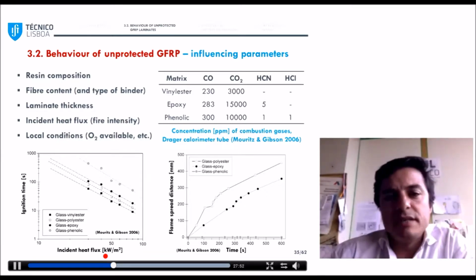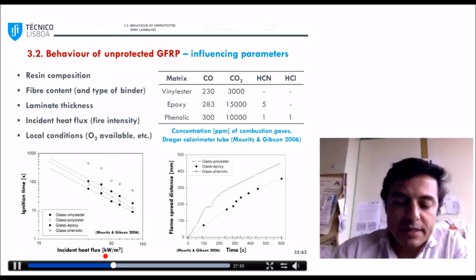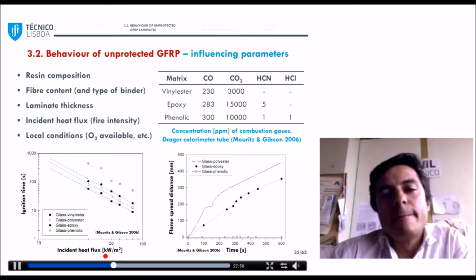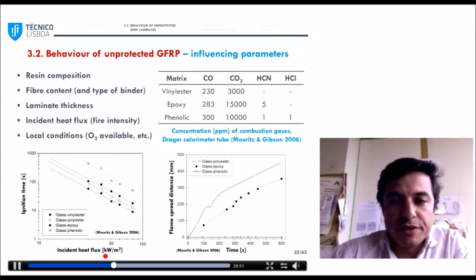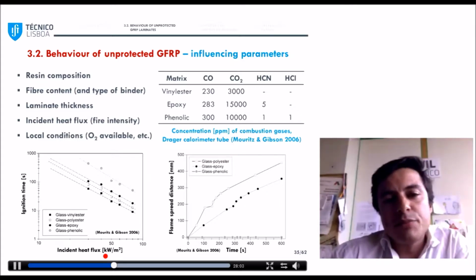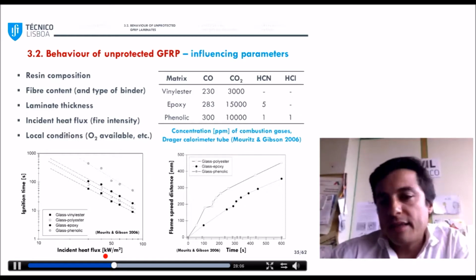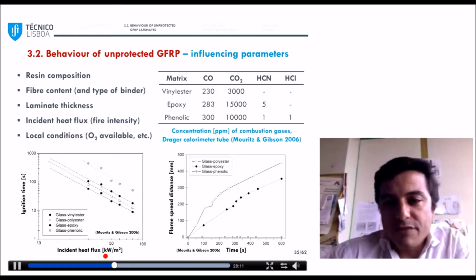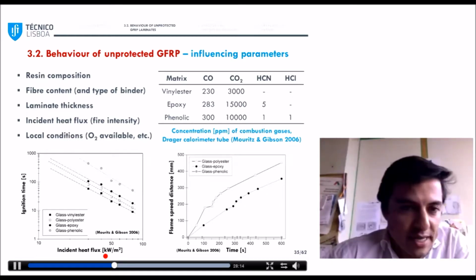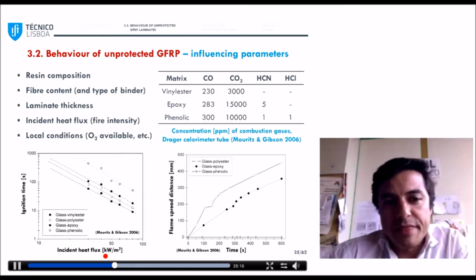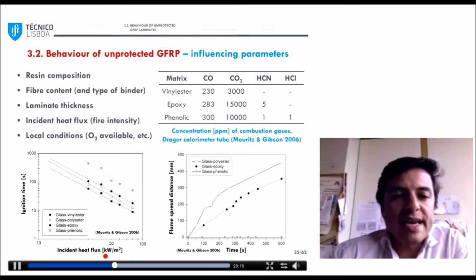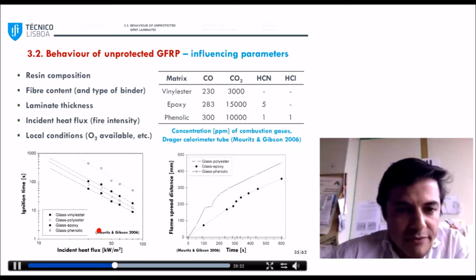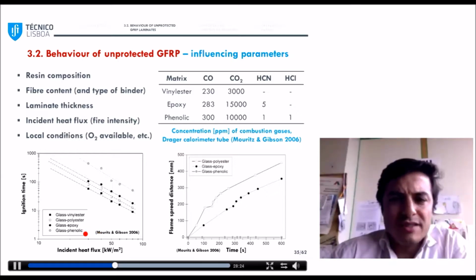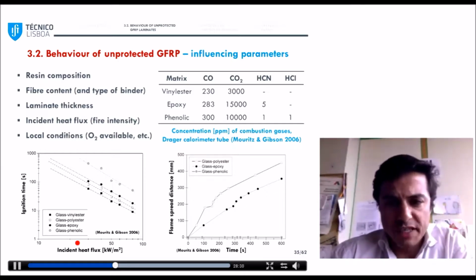So for unprotected GFRP material, and we will then see what happens when we use protections, there is plenty of literature from different industries, and previous results basically show that the fire reaction behavior is not good, and it depends on several parameters, namely the type of resin, the fiber content, the laminate thickness, the incident heat flux, and local conditions.